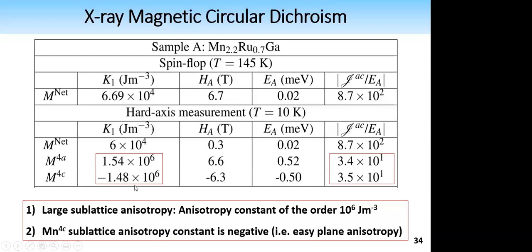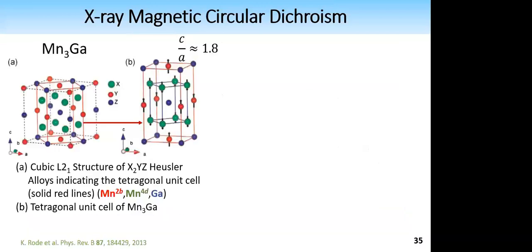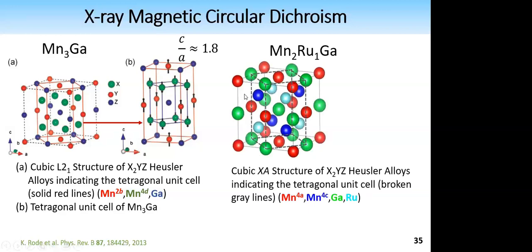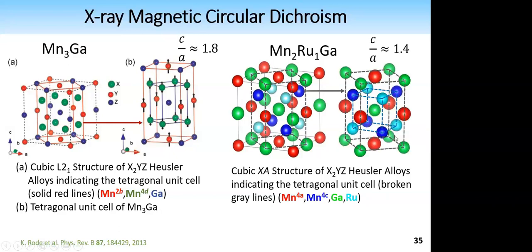However, just a note on the magnitudes, I want to make a comparison with manganese 3 gallium. Here I am showing on the left the cubic Heusler structure, which can be considered in its tetragonal representation, which is marked with the red solid lines. And on the right-hand side is the DO22 manganese 3 gallium tetragonal structure with a c/a of about 1.8. Now MRG, which is in its cubic representation, can also be represented tetragonally, which I have marked with these gray broken lines. Here I've isolated it. Looking at the tetragonal representation of MRG, we get a c/a of about 1.4. So there is obviously a difference between these compounds in tetragonal distortion.